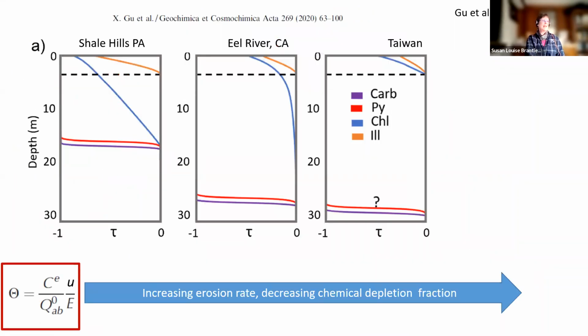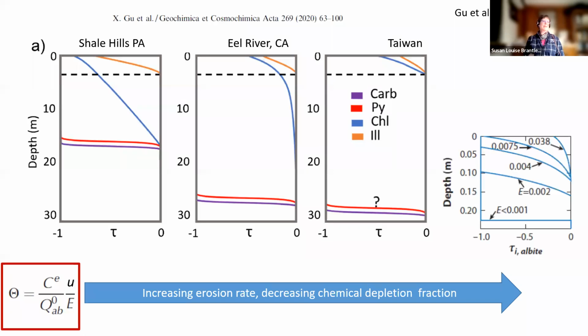And when we look at the tau plots, it looks just like we were predicting with our models. So here's the pyrite and the carbonate, it has enough time to totally dissolve away. Here's the pyrite and the carbonate, totally enough time to dissolve away in California. This is Shale Hills, pyrite and carbonate. We don't have complete control here in this Taiwanese system, but we know that the pyrite is gone by the land surface. So in effect, the erosion rate increases by 100-fold, but the pyrite and carbonate are still so reactive that they're still making patterns that look like this, making reaction fronts that look like this.